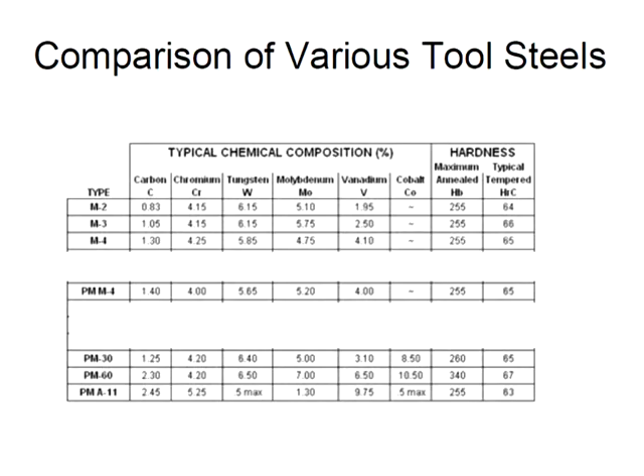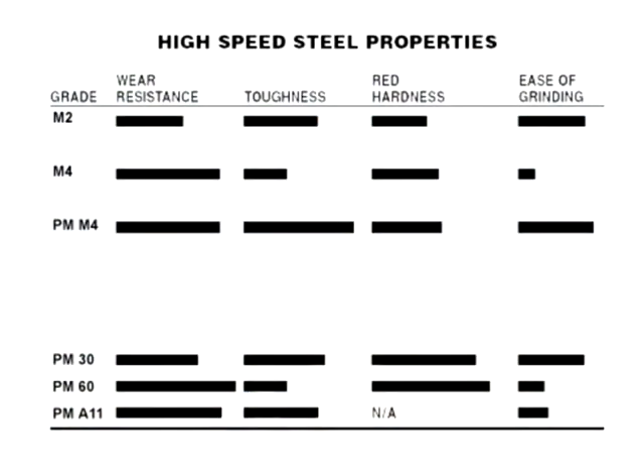You go down to the bottom, and what those are, the PMs, like that PMA11, a lot of people do a PMV11, they're special alloy, similar to that. Those are all powdered metal grades, the bottom 4. Powdered metal is very nice, and I'll go into the details of your powdered metal and what makes it superior. Your high speed properties typically, the toughness, the red hardness is what is nice here. Red hardness is when the tool gets hot at the tip while cutting, it resists temper back or softening. And you see they're all pretty good. Your powdered metals are pretty good too.